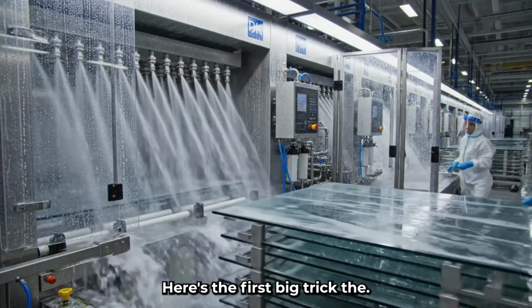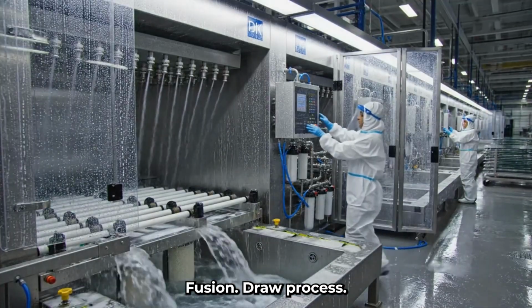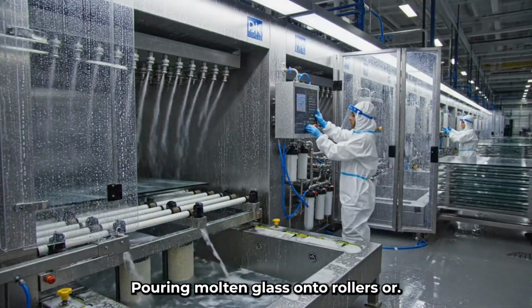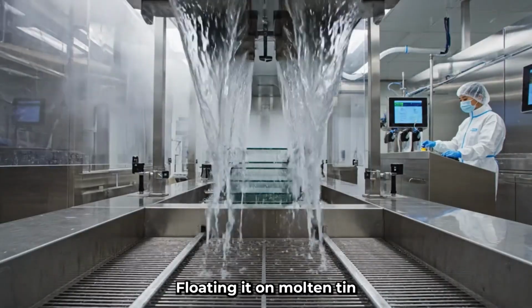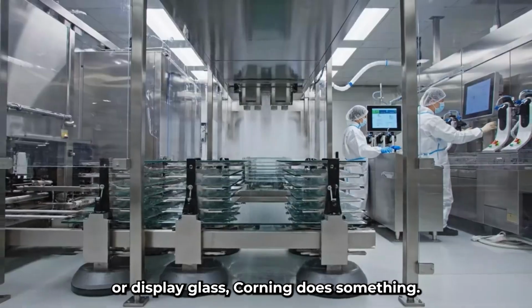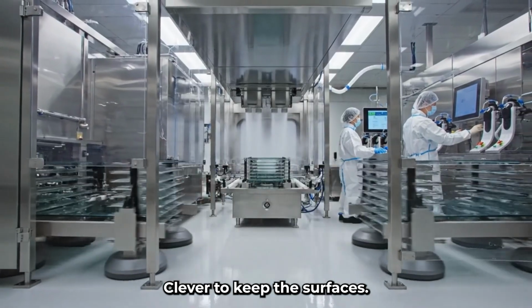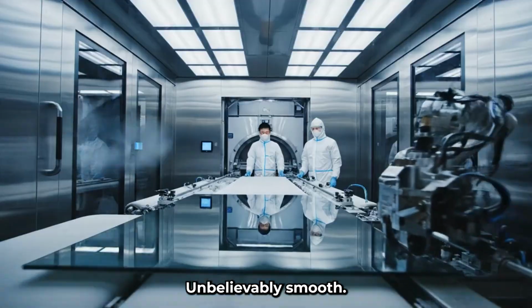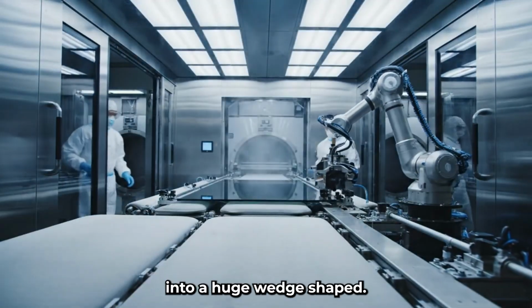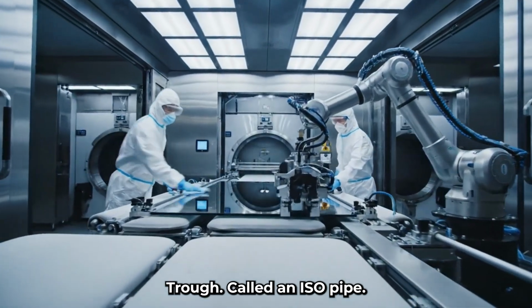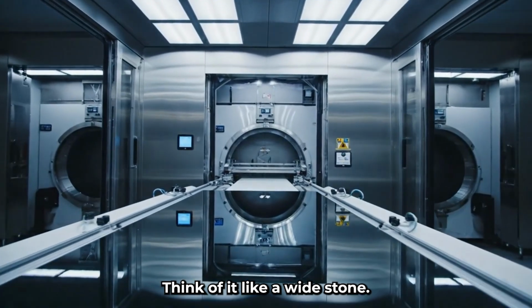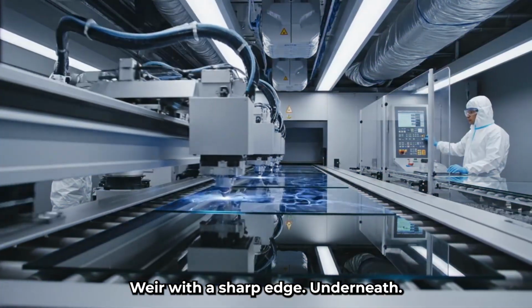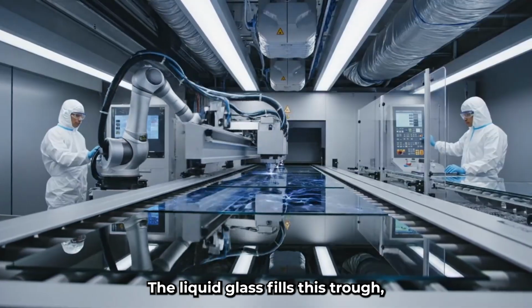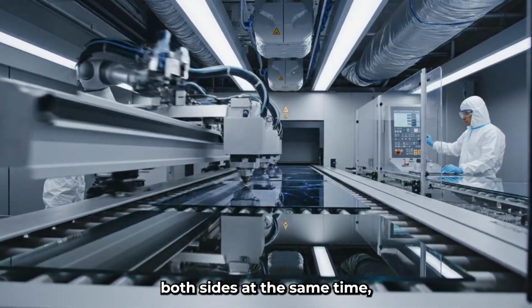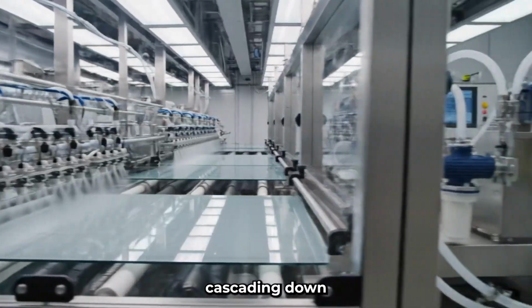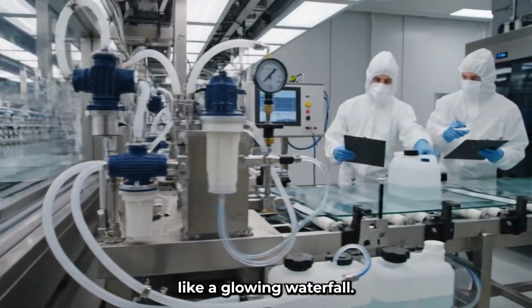glass. Here's the first big trick: the fusion draw process. Instead of pouring molten glass onto rollers or floating it on molten tin like typical window or display glass, Corning does something clever to keep the surfaces unbelievably smooth. The molten glass flows into a huge wedge-shaped trough called an isopipe. Think of it like a wide stone weir with a sharp edge underneath. The liquid glass fills this trough, then gently overflows both sides at the same time, cascading down in two even sheets like a glowing waterfall.